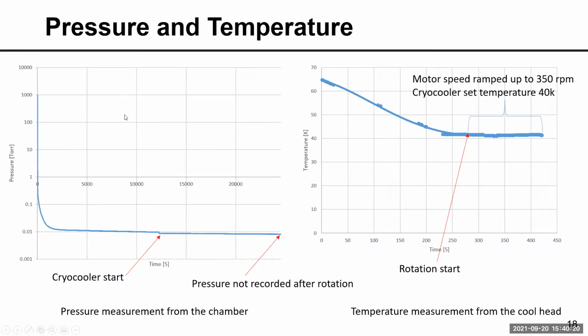So we did some initial experiments. What it shows is the pressure drop in the chamber and then the temperature drop. In the initial test we rotated the cryocooler and the sample to 350 RPM, and we were able to keep the sample at 40 Kelvin while it is rotating. So it is a success, showing that we can use the cryocooler that we have in the lab in a real machine, but we should rotate up to 3,500 RPM to benchmark the result and see that it can operate at higher speed.